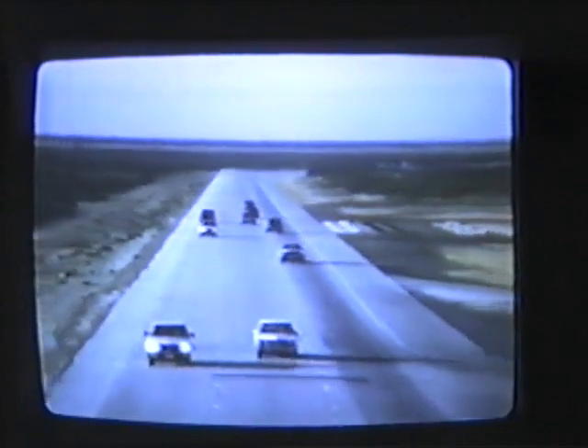Durability tests are run at much higher than normal highway speeds, sometimes over 100 miles an hour, under loads which exceed any they are likely to encounter in service. But in the final analysis, the tire must be tested on actual vehicles in the real world. At its 6,000-acre test center near Fort Stockton, Texas, and at similar facilities in Europe, Firestone subjects its prototype tires to a broad spectrum of tests.